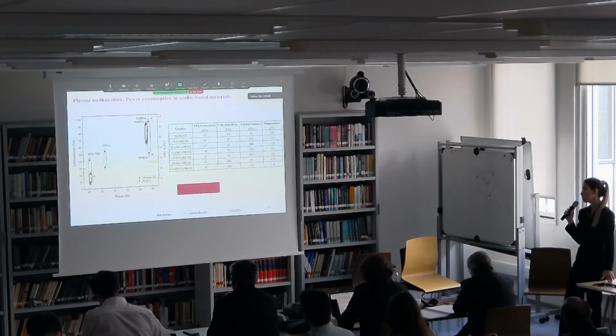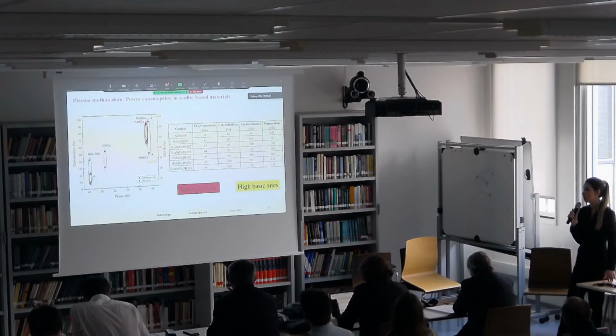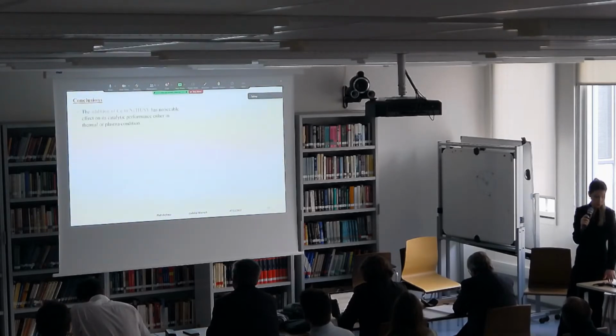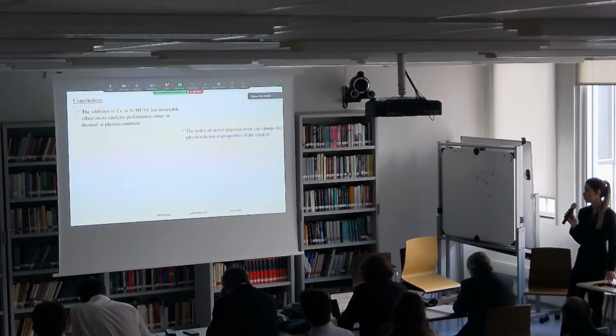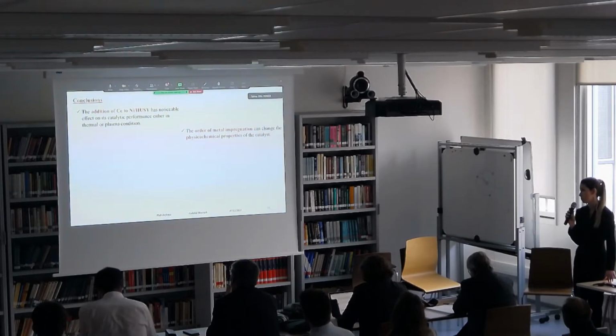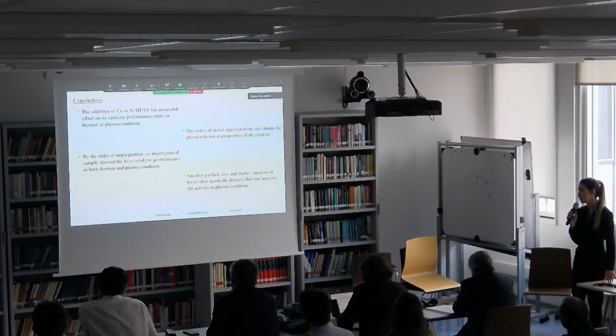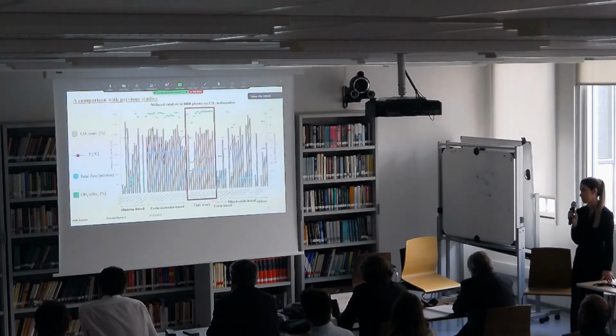The important properties that were playing an important role here were a small particle size and a high amount of basic sites. So to conclude this part, we already saw that with the addition of ceria in general to the catalyst, the catalytic performance improved. The order of metal impregnation actually plays an important role in the physicochemical properties of the catalyst, while the co-impregnated sample had the best catalytic performance. A smaller particle size and higher amount of basic sites are the important features for the activity in plasma condition.